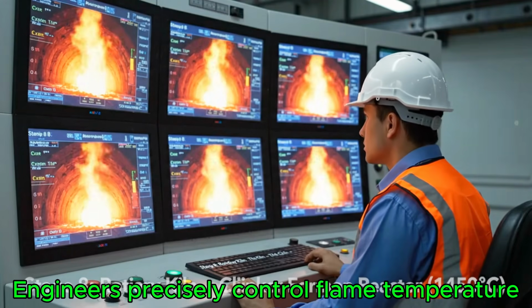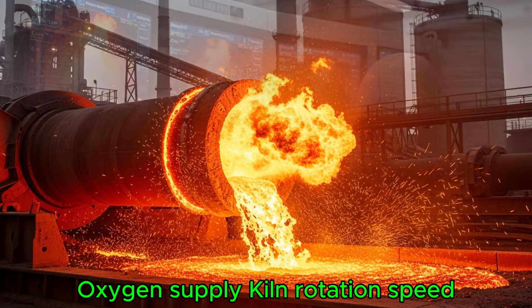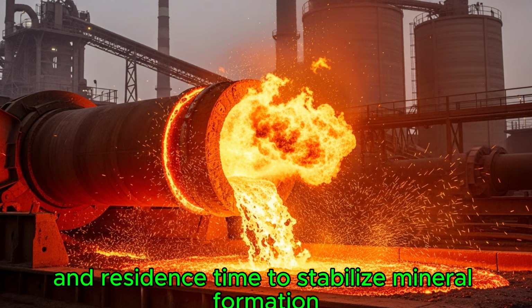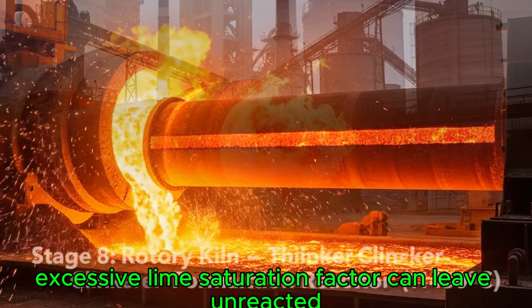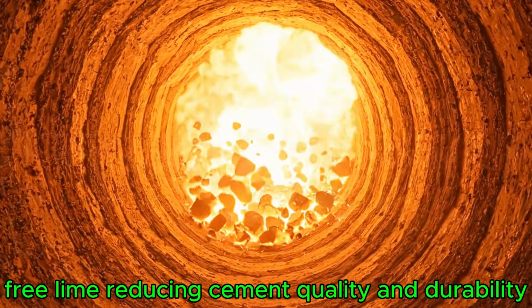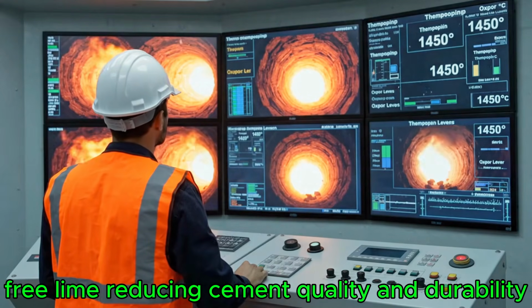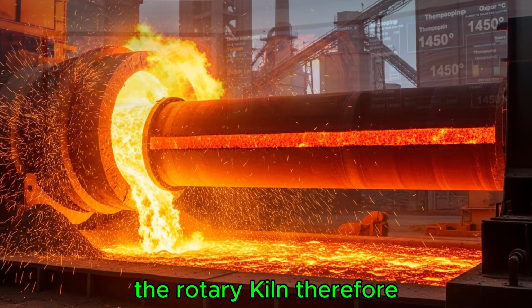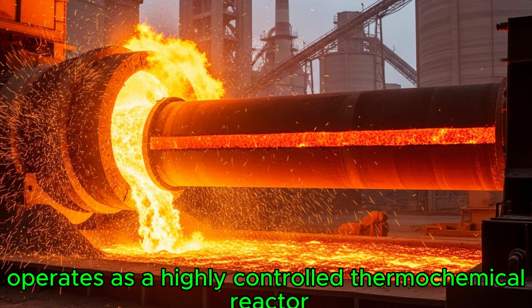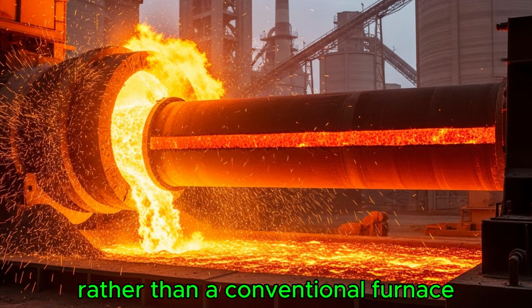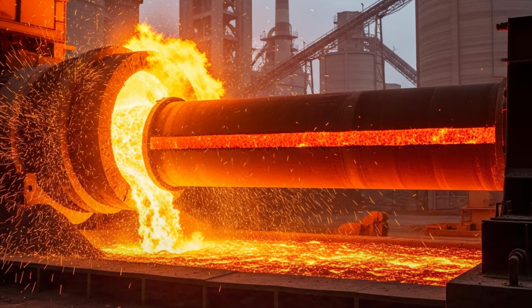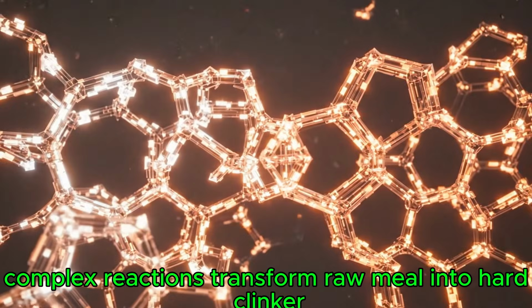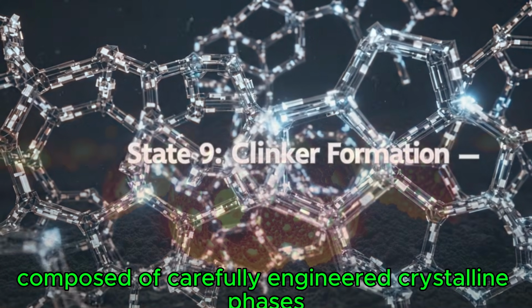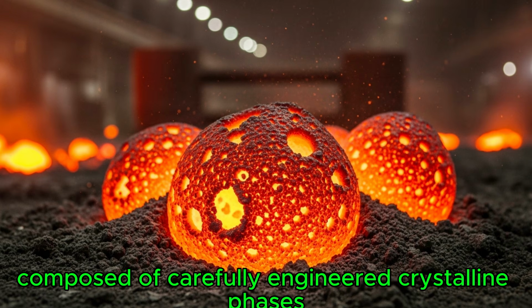Engineers precisely control flame temperature, oxygen supply, kiln rotation speed, and residence time to stabilize mineral formation. Excessive lime saturation factor can leave unreacted free lime, reducing cement quality and durability. The rotary kiln therefore operates as a highly controlled thermochemical reactor rather than a conventional furnace. Inside the burning zone, complex reactions transform raw meal into hard clinker nodules composed of carefully engineered crystalline phases.